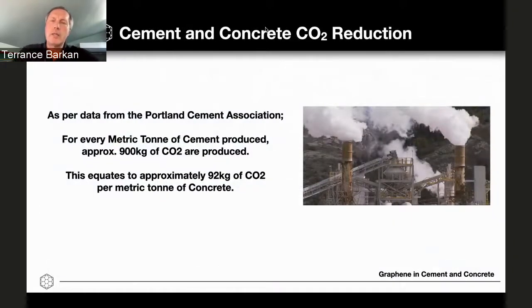Another application area that's quite exciting, as I mentioned, was concrete and cement. Every metric ton of cement that is produced, so you bake that material, you produce approximately 900 kilos of CO2. So it's almost a 1-for-1. When you make cement, you make CO2. That's about 92 kilos of CO2 per metric ton of concrete, because the cement is diluted with aggregates into the final concrete product. So 92 kilos of carbon tend to find their way in every metric ton of concrete. Concrete is used at a higher volume than any other material on the planet, with the exception of water.